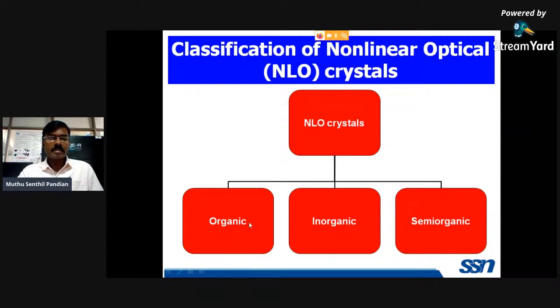The advantage of organic single crystals is that the SHG efficiency, the second harmonic generation efficiency, of most organic single crystals is very high due to van der Waals forces. But the problem with organic materials is that we cannot easily grow very good quality and bulk size single crystals. That is one of the big drawbacks in the growth of organic single crystals. With inorganic single crystals, we can grow very high quality and bulk size crystals with higher mechanical stability and higher laser damage threshold. KDP and ammonium dihydrogen phosphate are inorganic materials. But the problem with inorganic materials is that the SHG efficiency is less compared to organic materials. So in order to get the advantages of both organic and inorganic materials, several researchers are now working in this semi-organic category. I will show you in the next few slides.